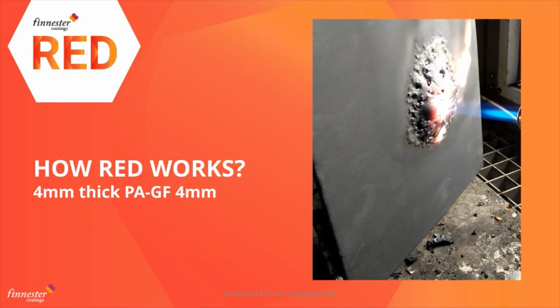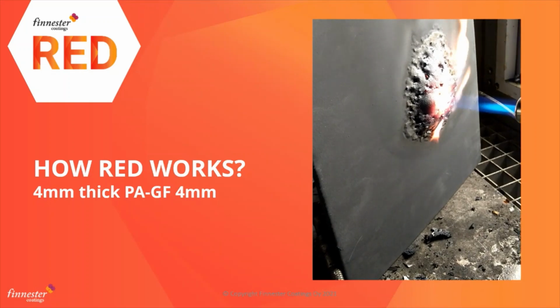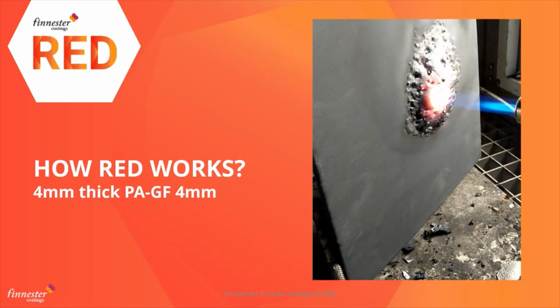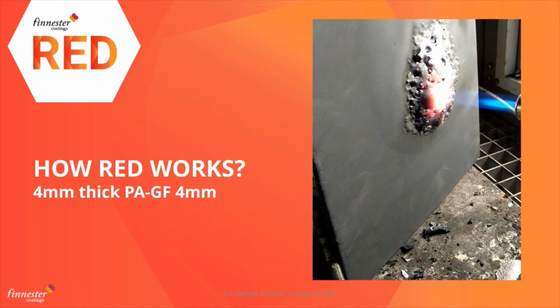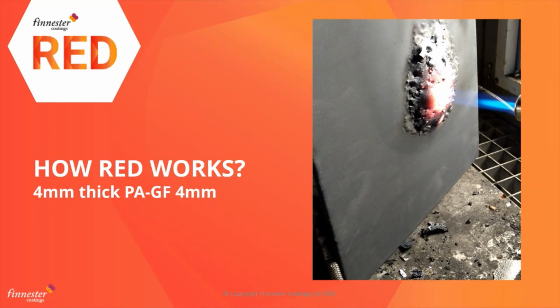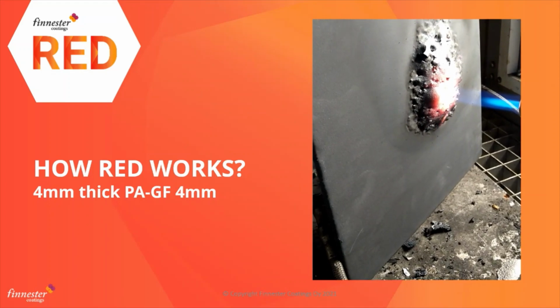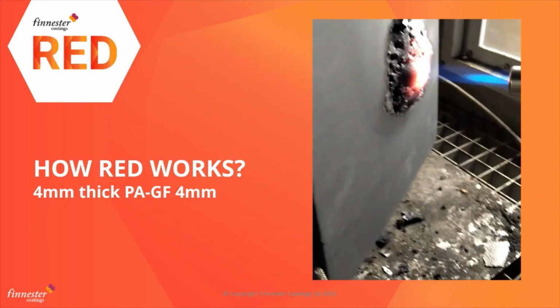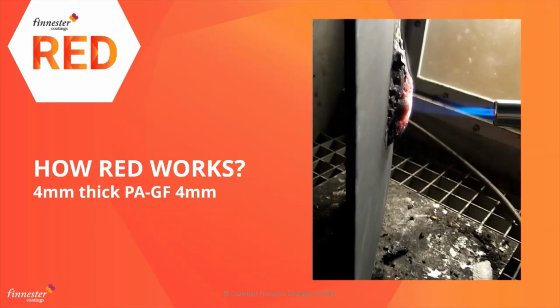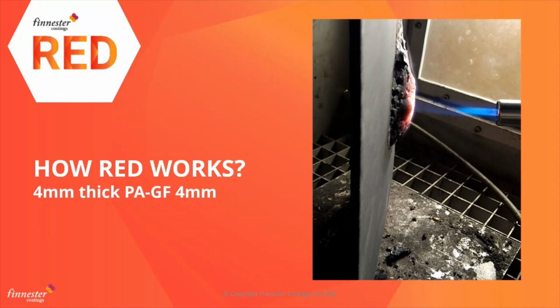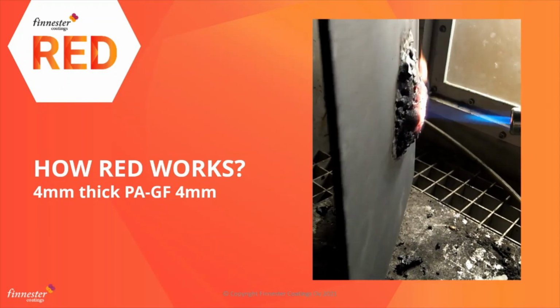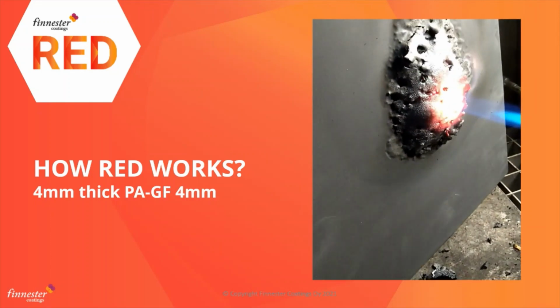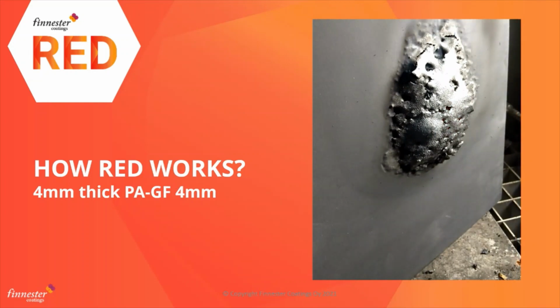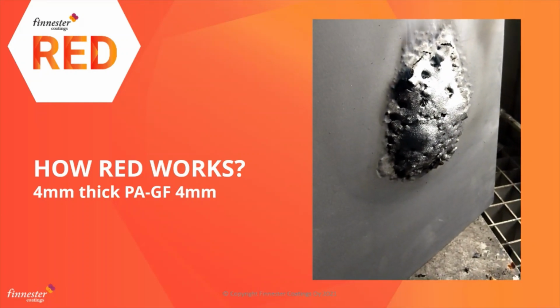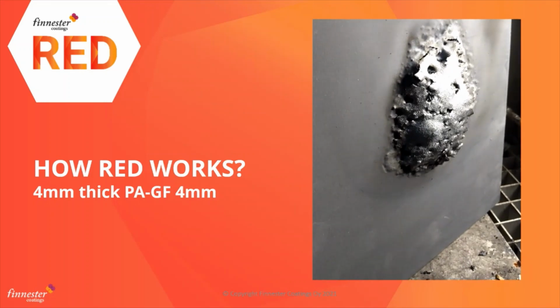If not, you can see that later when we distribute the material. But you can see that you can still keep burning it, and it's just burning stone, well, ceramic material. And if you look from a different angle, you can actually see how much the expansion has happened, and the ceramic shield is protecting the expansion. Without the ceramic shield on top, the expansion would just be uncontrolled, but in this case, it's controlled and stays stable. And when you remove the flame, as you see, the flame is not spreading, it's just holding. When you remove the flame, it immediately extinguishes and leaves the hard ceramic protective shield on top.